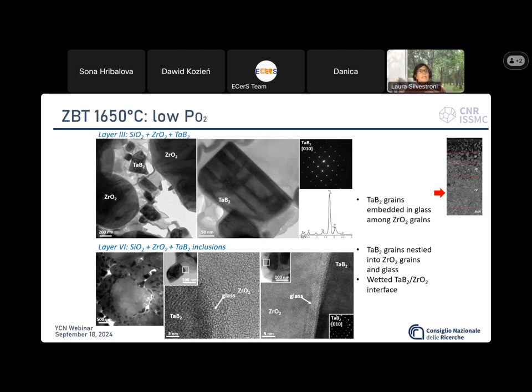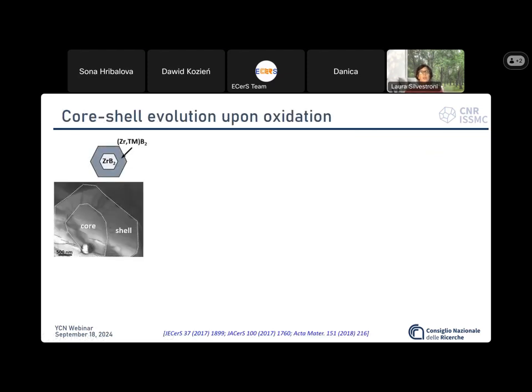But the problem is that, as long as we are at low oxygen partial pressure in the subscale, these tantalum diboride particles are protected and very effective. However, as the oxidation becomes more aggressive, increasing the oxygen or the temperature, tantalum diboride oxidation occurs and forms tantala, which is beautiful from a microstructural point of view, but it's accompanied by a very large volume expansion that destroys the zirconia skeleton. So in an extreme simplification, this is how the core shell evolves upon oxidation.